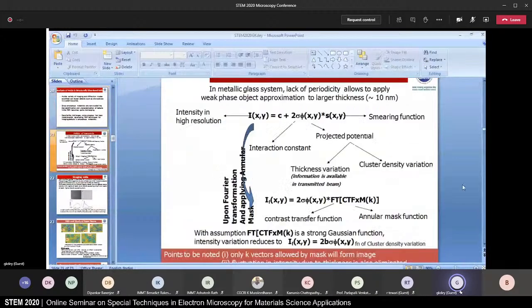This is the intensity of the beam in the high resolution mode, and it comprises, besides other things, the projected potential of the crystal, which is most important, and that actually reflects the structure of the material. In addition to that, we have other things like the smearing function, interaction constant, and so on and so forth. Here we also have a component of the effect of variation in the thickness of the foil. So if we use a filter, which is an annular filter, it may be able to filter out all this from the important information, that is the projected potential. And by applying an annular filter, it has been possible to reduce this equation to this form, where only the projected potential part, which actually reflects the structure, is depicted. So we use an annular filter by doing a reverse Fourier transform of the image.